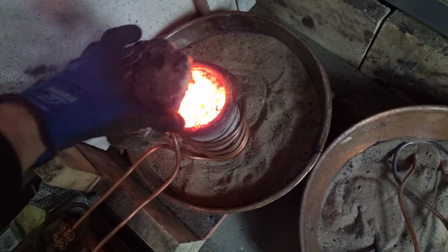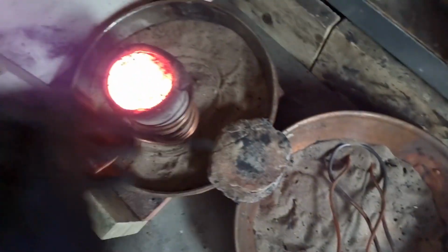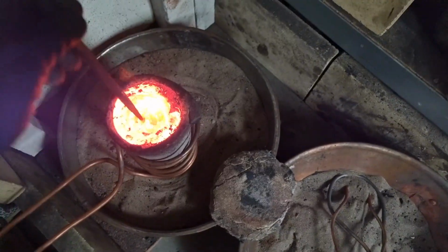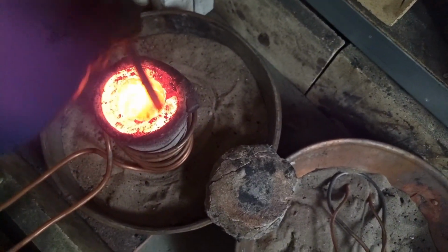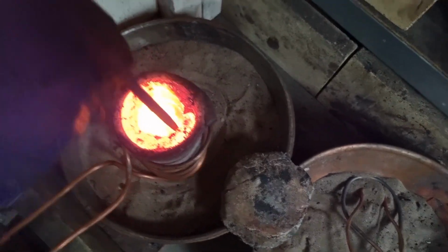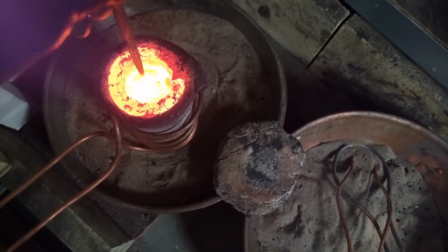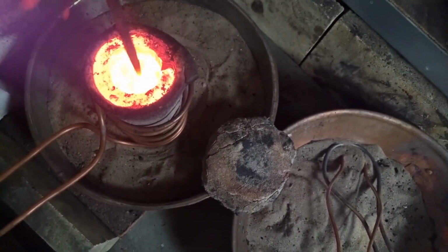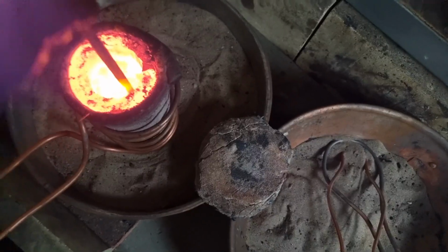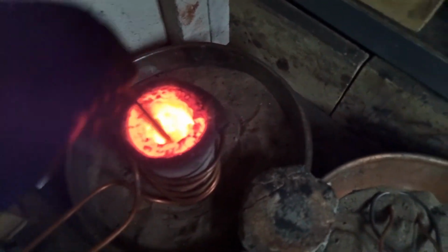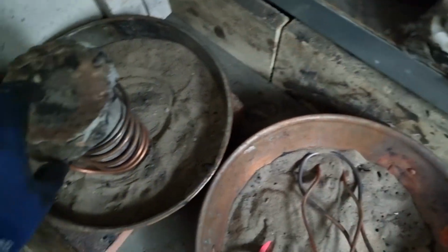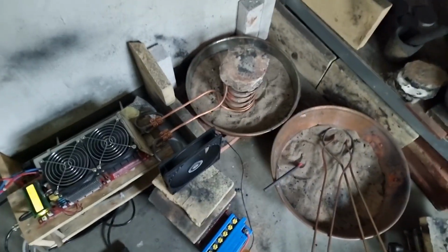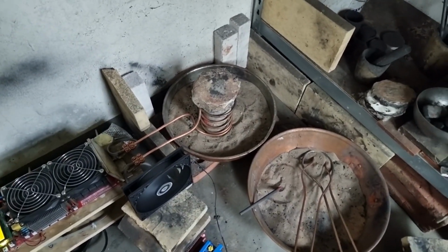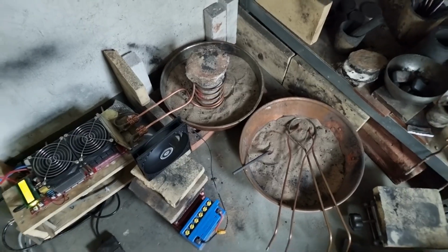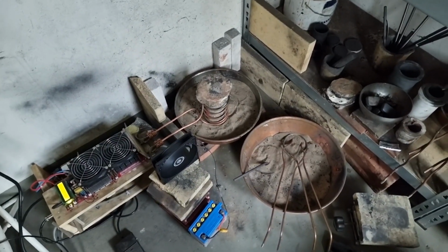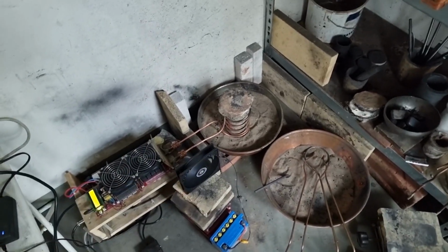As the temperature is rising, that iron powder is gonna combine with the graphite, carburizing that iron, and then slowly forming our cast iron. Gotta stir it from time to time, but you see that the level is dropping here, so that shows us that slowly the iron is melting, forming that cast iron. So let's wait a bit more, and then we should be able to extract our liquid iron out of that crucible.